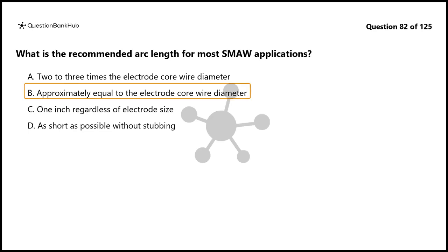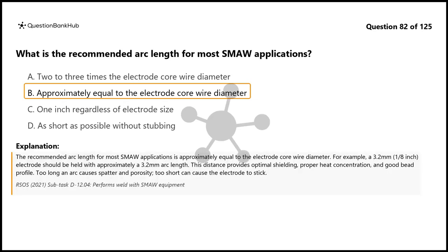The correct answer is B. Approximately equal to the electrode core wire diameter. The recommended arc length for most SMAW applications is approximately equal to the electrode core wire diameter. For example, a 3.2 mm, 1/8 inch, electrode should be held with approximately a 3.2 mm arc length. This distance provides optimal shielding, proper heat concentration, and good bead profile.